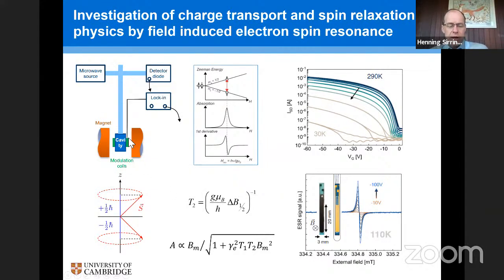And so I want to show you an experiment now where we have made a field effect transistor with such a conjugated polymer system, and then we put this FET into an ESR cavity, and measure the ESR spectrum as a function of gate voltage on the FET. As you switch on the device, you can see here the increase in current as a function of gate voltage. As you increase the gate voltage, you induce more and more charge carriers in the organic system. And here you can see how the signal strength of the ESR signal increases as we increase the gate voltage. So this allows us to measure the spin relaxation properties of these charge carriers that we induce with the gate, as a function of carrier concentration and as a function of temperature.